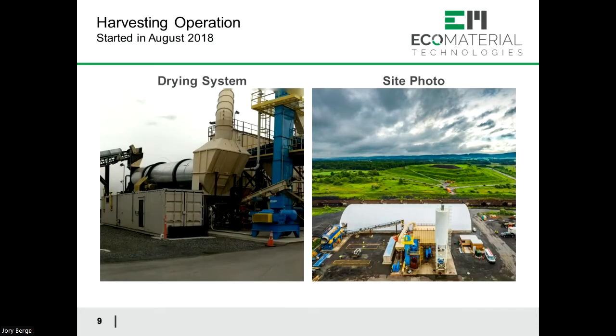There's kind of a site photograph of the impoundment. The big, pretty green stack in the background is the ash stack. And then on the left-hand side, you can see we use a trommel up front to remove larger agglomerations. It goes through a drying, then the bag house is there, and there's a vertical conveyor belt that takes it up into the silo after it's been sieved. And that particular one, we get good fineness on by just sieving it on a number 20.